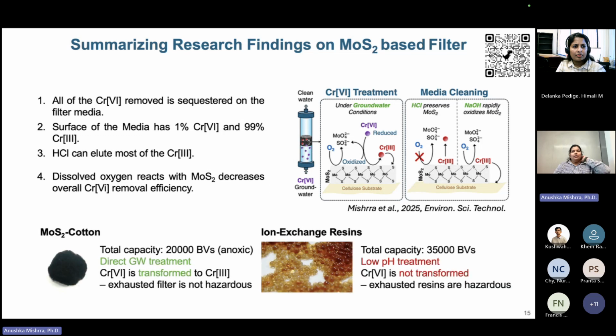So why is this important? This is important because currently in California, there are ion exchange columns being used to remove chromium-6. It's a very good technology because it can treat very high volumes of water, like 35,000 bed volumes, and if run in correct conditions, even higher.